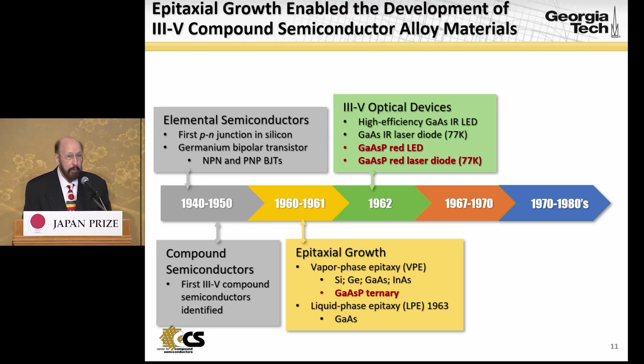In 1962, 4 important results were reported for 3-5 compound semiconductor optical devices. First, high-efficiency infrared gallium arsenide LEDs were reported by Bob Rediker's group at MIT Lincoln Laboratory. And later that same year, in 1962, Robert Hall at General Electric in Schenectady demonstrated the first infrared laser diode. As I mentioned, Professor Holonyak developed the first red LED that was commercialized in 1963. And also in 1962, a few months after the first injection laser in gallium arsenide, Professor Holonyak demonstrated the first injection laser in gallium arsenide phosphide, which at 77 Kelvin emitted in the red. So this is the beginning of the semiconductor laser diode.